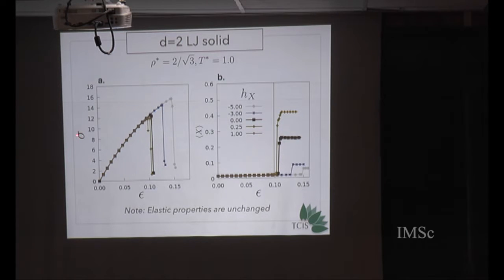So what happens? If you plot stress versus strain in the presence of field, then you can see that by changing the field from positive to negative over 0, you can change the yield point without changing the elastic constants. So if you had a colloidal solid, you can actually change the yield point of this colloidal solid without doing anything else. Okay? And now we have a very good definition of the yield point, because it is a dynamical transition and there is this collective coordinate that shows a jump. And this jump also depends on the value of the field. Okay? So this is again exactly an analogous transition.